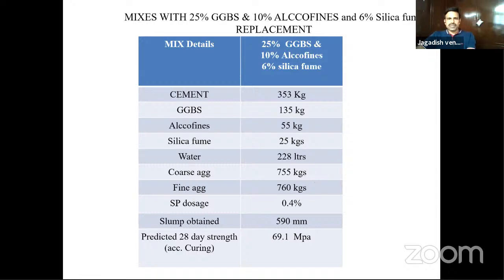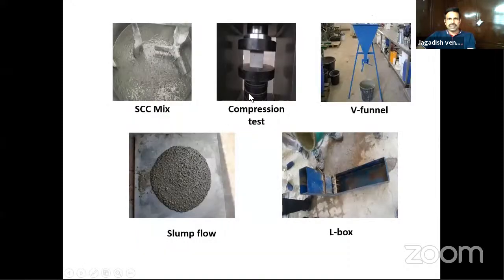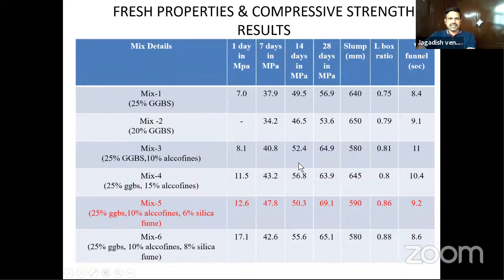So this is without fibers, around 69 MPa we got. We made an SCC mix and did all the tests: compression, V funnel, slump flow, L box test. These are the mixes you can see here. The first mix, the 28-day strength, you can see 56 MPa with 25% GGBS. And then next 20%, and then we got